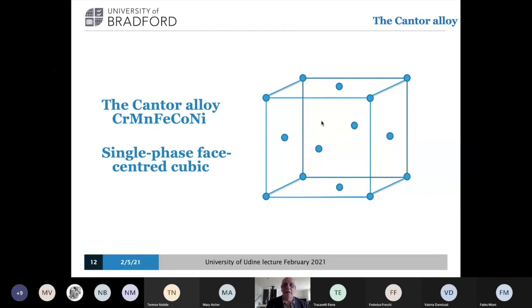Nobody would have predicted, and nobody did predict, that if you added 5 components like that, they would all dissolve into a single phase structure with that structure. What does it mean? It means that a fifth of the atoms are chromium, a fifth manganese, a fifth iron, a fifth cobalt, a fifth nickel, and they're all distributed on this structure at random. So a fifth of them are each of those different elements. Nobody would have predicted that. Nobody did predict it. Only nickel of those has this structure in its pure form. So it was a complete surprise.